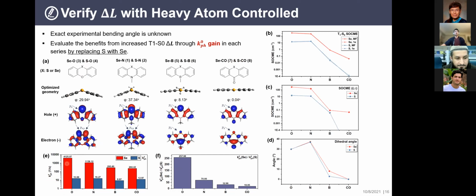And we divided the phosphorescence rate of the selenium derivative by the phosphorescence rate of the sulfur derivative. This is how we characterize the effect from replacing the atom, how much gain you will have in terms of phosphorescence rate. And we found that when you have a larger dihedral angle, which means a larger angular momentum change, you will have a larger gain from replacing your heavy atom with an even heavier atom. So in this way, we think we pretty much form a very sound story. And so we write this manuscript and then submit.